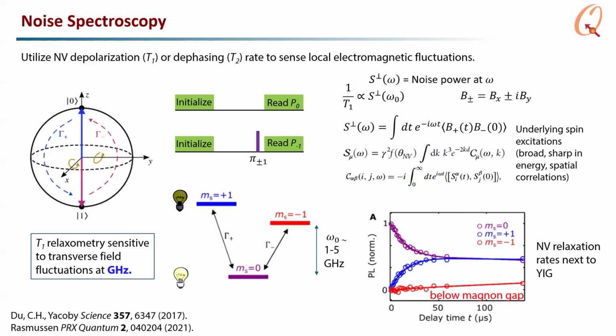the m sub s equals 0 in purple. After I polarize in that state, it decays into the m sub s equals +1, but not really into the m sub s equals -1. And that's due to the fact that the m sub s equals -1 is below the magnon band gap at this magnetic field. This was at a particular magnetic field. So m sub s +1 was above the band gap. M sub s equals -1 was below the band gap.